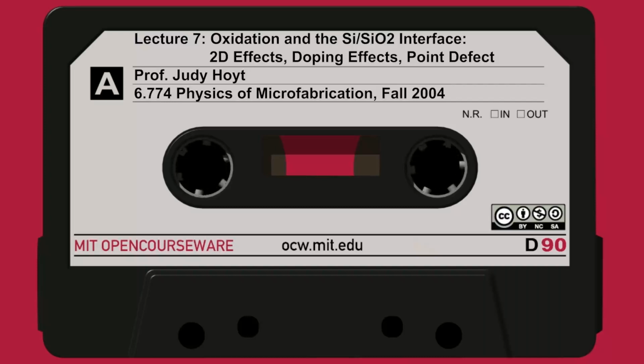This particular one was oxidized in dry oxygen at 875 for about 10 hours. And you can actually see the lattice fringes in the single crystal silicon that remained. What was really neat is what Harvey found: depending on the temperature that he did this, he could oxidize that pillar and it would stop. The oxidation rate would go way down when you got down to a certain diameter pillar.